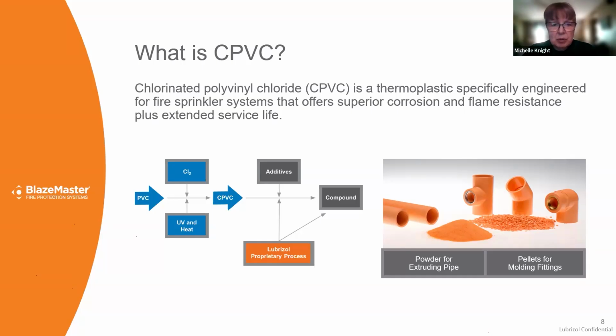So it makes it more suitable for hot water plumbing pipe and also fire sprinkler piping. You can't use ordinary PVC for fire sprinkler piping. You need CPVC because it's more fire resistant due to the extra chlorine. And I just want to point out here, again, we're making CPVC using pretty high intensity UV light, and we're not degrading it during that process. So a little bit of UV from the sun is certainly not going to hurt the CPVC molecule.